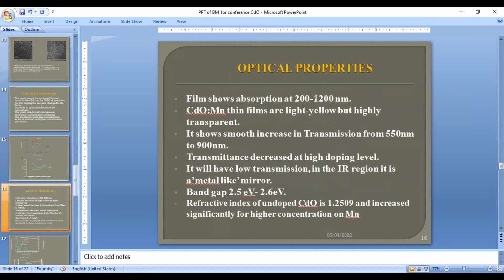The optical properties: the film shows absorption at 200 to 1200 nanometer. The thin films are light yellow but have high transparency. It smoothly increases the transmission from 550 nanometer to 900. Even though the film shows absorption capacity from 200 to 1200 nanometer, the transmission will be very good in 550 to 900 nanometer.